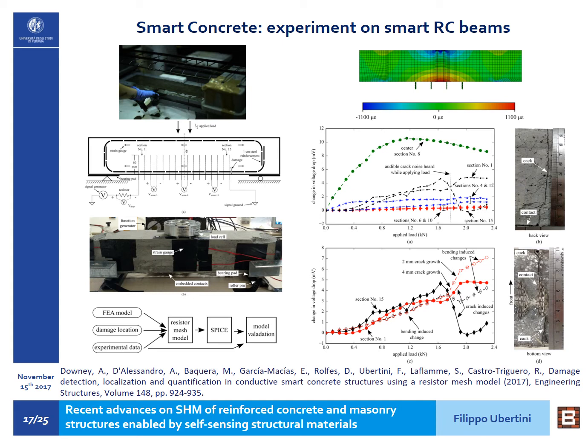in a very initial part of the diagram, we have increases in voltage drop with increasing load, and those are essentially due to the deformation that the load determines in the material, and here what dominates is the tensile strain that results in a local increase in electrical resistance because the electrodes are in the bottom part of the beam. And then at a certain point, when a damage forms, a shear crack starts to form outside of the region where we have the electrodes, we have sudden changes in the voltage drops across different sections of the beam.